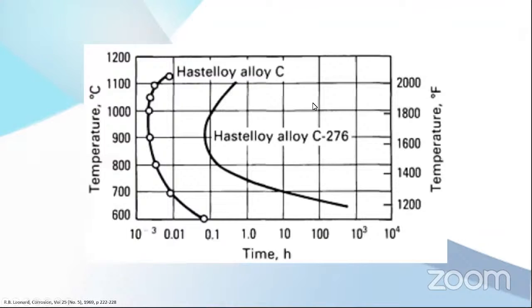And it's not only stainless steel, also nickel alloys. Although it's very rare to happen, nickel based alloy also can have this sensitization. It's not the same curve, but the same concept. So when you cool the metal and it contacts the nose, then you will have this sensitization. So try to avoid long cooling time, so that it will not contact the nose.